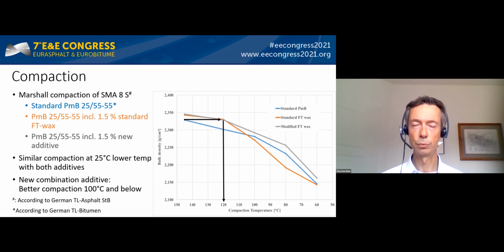Compaction was done at 145, 120, 100, 80 and 60 degrees. The diagram shows that equally both additives reduced the compaction resistance and resulted in improved density. And we can see that at 120 degrees, we obtained the same density as with the hot mix reference at 145. This means 25 degrees temperature reduction were possible without compromising compaction. We can also see that the new combination additive gave the best compaction at 100 degrees and below.